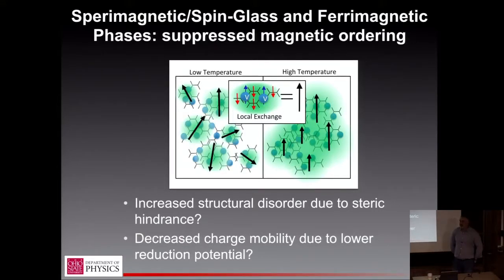When you say that this order somehow is stabilized by these new carriers introduced by temperature, you don't mean any kind of RKKY stuff. You mean something different, right? I don't know. It's RKKY-ish. RKKY assumes band carriers that are oscillating, and these are hopping carriers, right? So they can't be doing exactly that. You're just saying that somehow the energy of these hopping carriers gets reduced enough by uniform magnetization in order for that magnetization to get uniform. Yeah, that's one way to say it. Another way to say it is, if you look at the typical length scale, the average length scale for a carrier in this hopping regime is temperature dependent. And as that length scale gets to be large on the scale of this inhomogeneity in the magnetization, it helps to anneal it out.